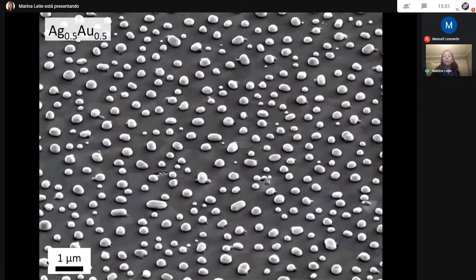Okay, so this is an example of an SEM, a scanning electron microscopy image, of how one of those samples looks. In this case, a mix of 50% silver and 50% gold. You can see that the method is not perfect. I like showing a zoom out on purpose. We did extensive statistics on that. You can see that sometimes there is some incomplete coalescence process going on, like in this particular case.